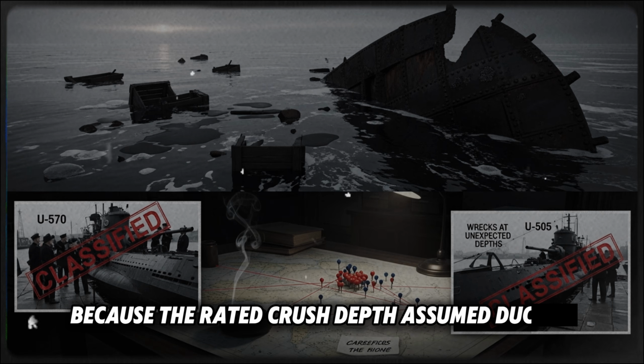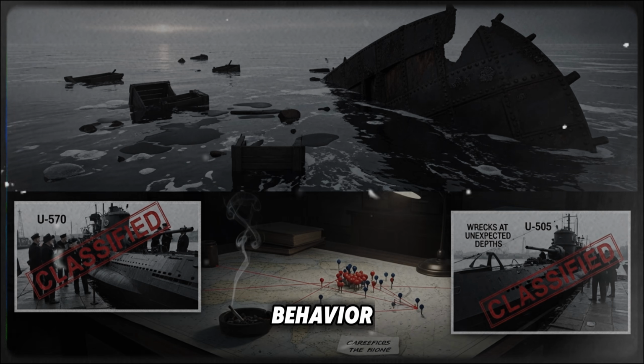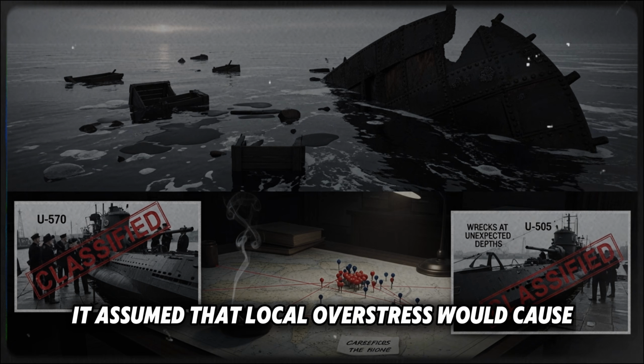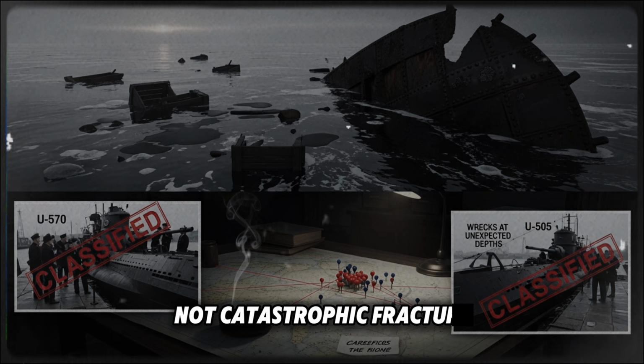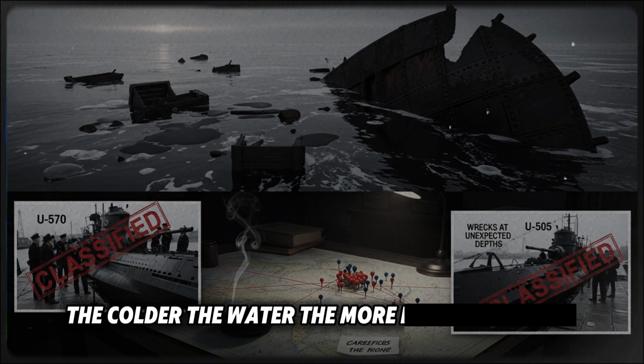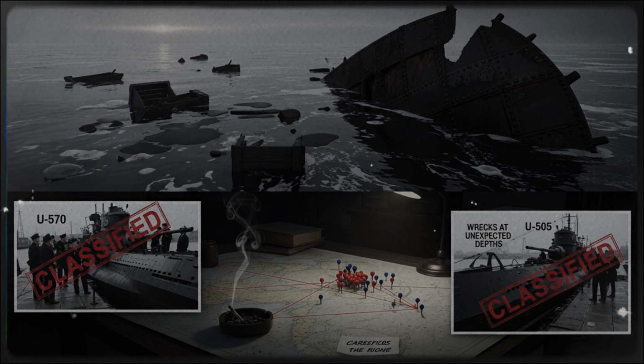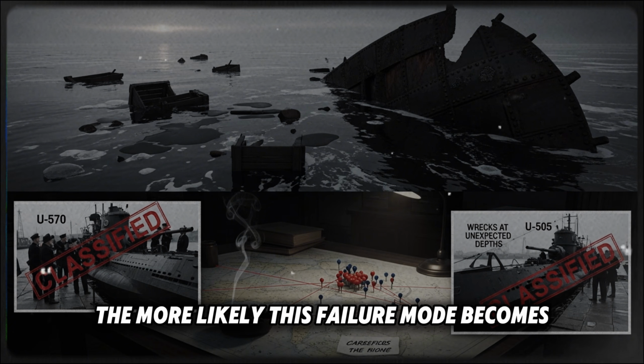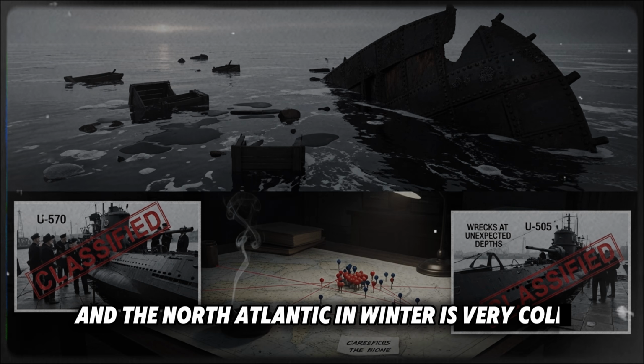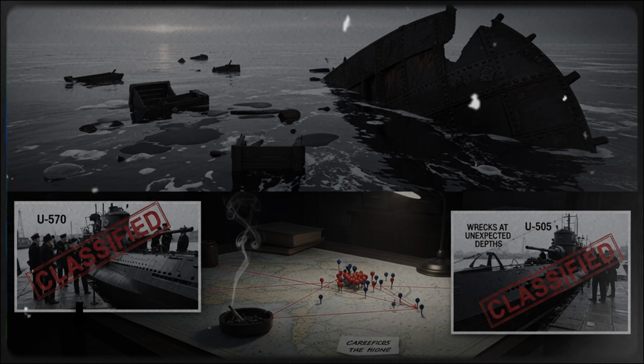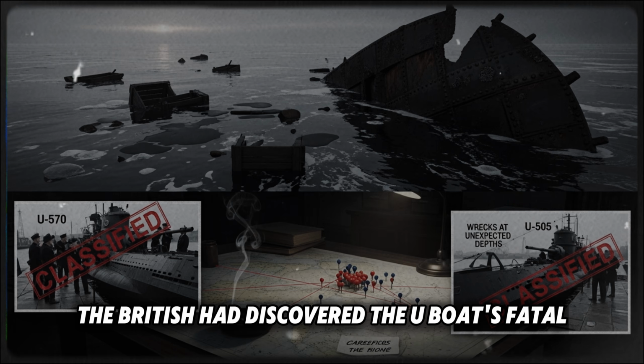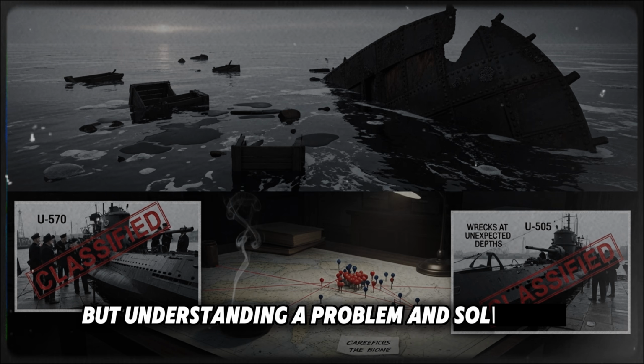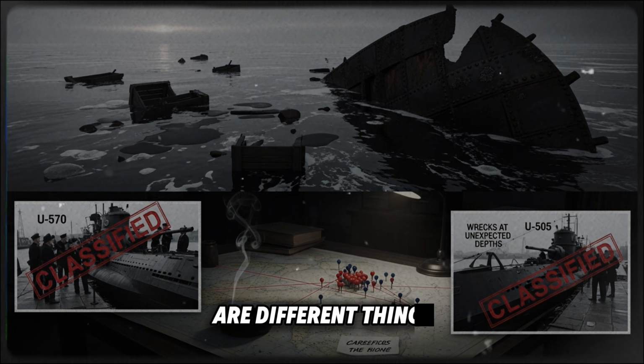Because the rated crush depth assumed ductile behavior, it assumed that local overstress would cause yielding, not catastrophic fracture. The colder the water, the more brittle the steel, the more likely this failure mode becomes. And the North Atlantic in winter is very cold indeed. The British had discovered the U-boat's fatal weakness, but understanding a problem and solving it are different things.